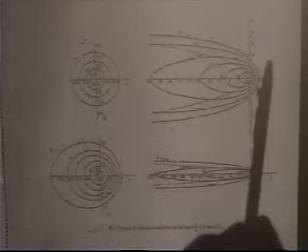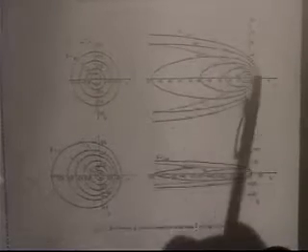So here, if I were to look out in the y direction on this one, which is moving faster, this little dashed line is the locus of where these distorted ellipses reach their maximum y extent, plus y and minus y. You can think of it as a wave behind a boat or something, is the way Niels used to describe it, spreading out. It's basically diffusing out. In fact, it is a parabola, as far as that goes. It's diffusing out as square root of t.